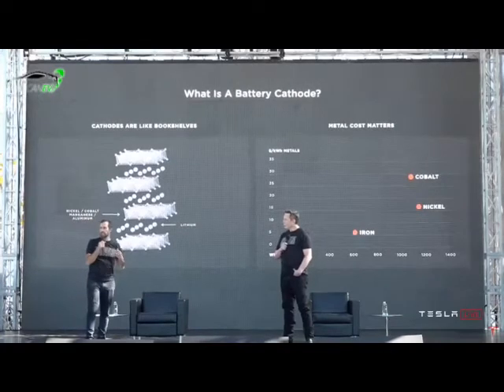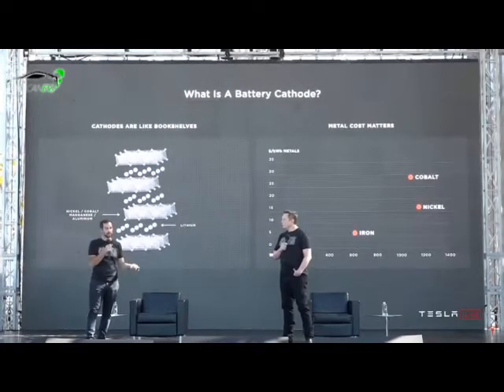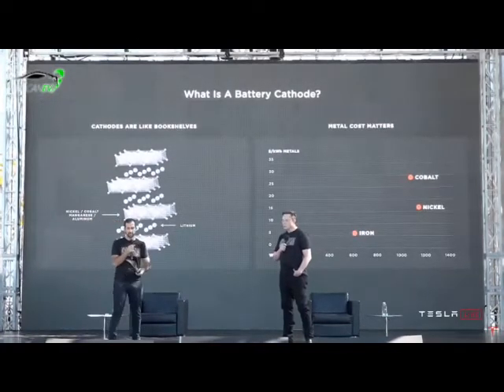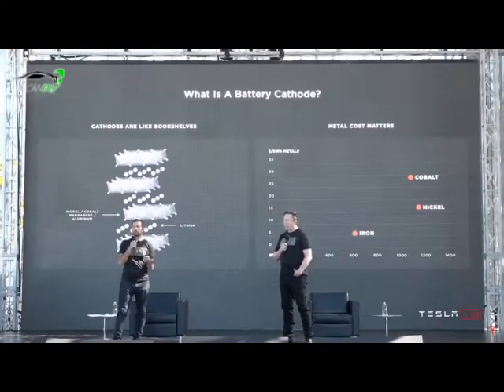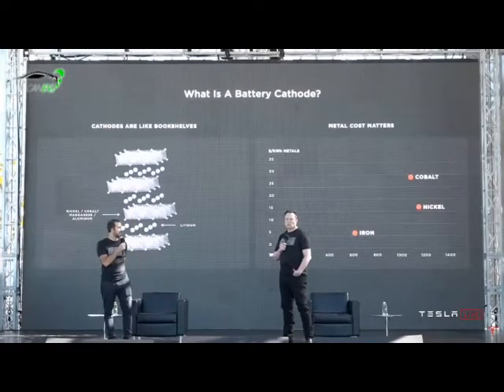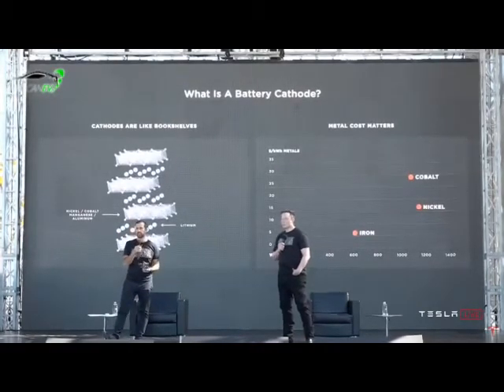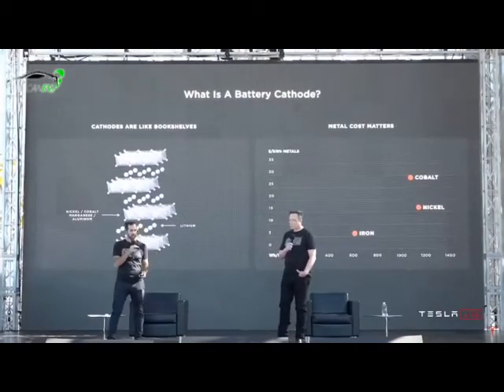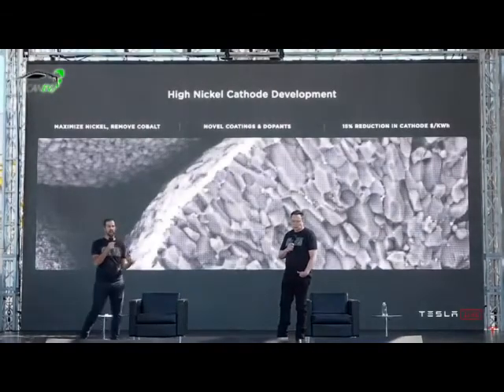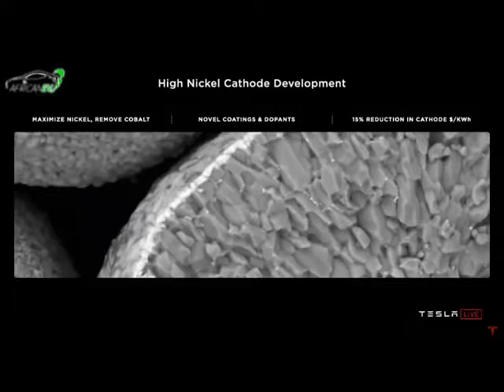And that's why increasing nickel is a goal of ours and really everybody's in the battery industry. But one of the reasons why cobalt is even used at all is because it is a very stable bookshelf. And the challenge with going to pure nickel is stabilizing that bookshelf with only nickel. And that's what we've been working on with our high-nickel cathode development, which has zero cobalt in it. Leveraging novel coatings and dopants, we can get a 15% reduction in cathode dollar per kilowatt hour. Big deal.